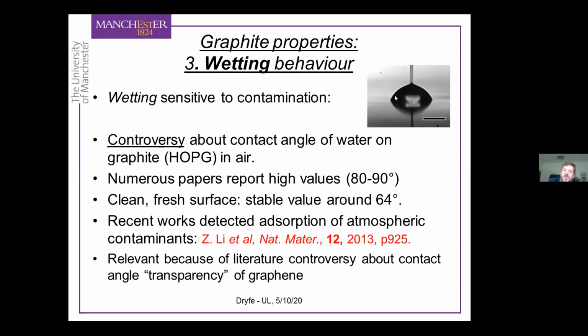So you can see that we do these experiments so that we can measure the contact angle of this aqueous droplet on graphite, which I should say is in air. And basically, we measure consistently a contact angle of about 64, plus or minus 2 degrees for water on graphite in air. Now, you'd think that'd be a very simple experiment and that would be an established value, but it's not. If you look in the literature on the contact angle of water and graphite, you can almost find any number that you want.